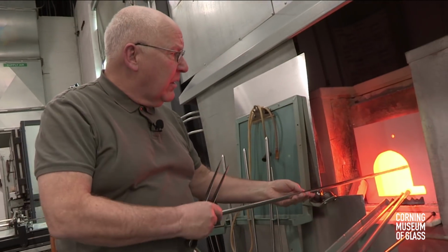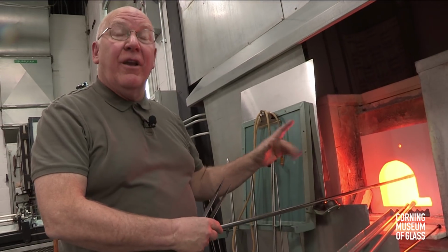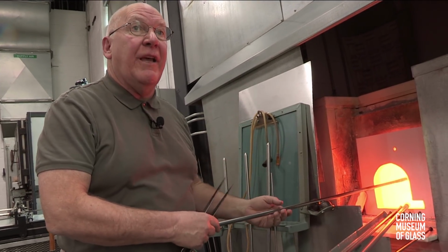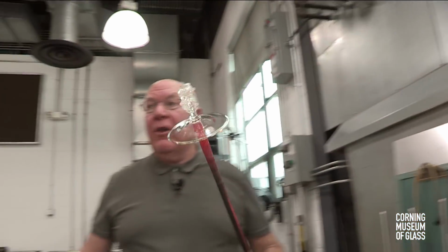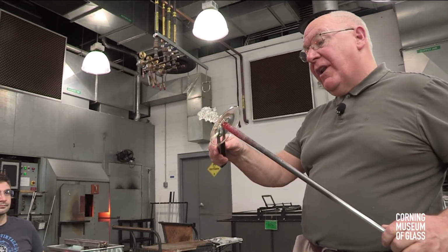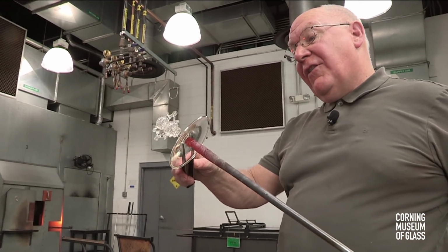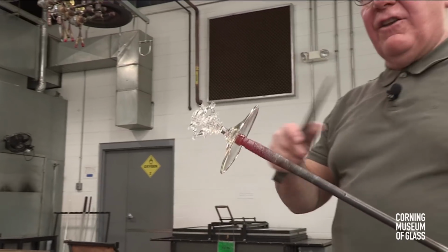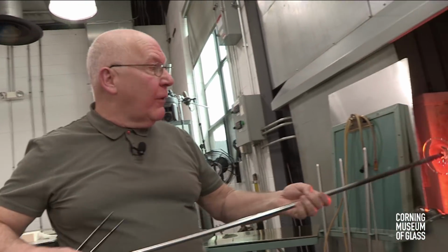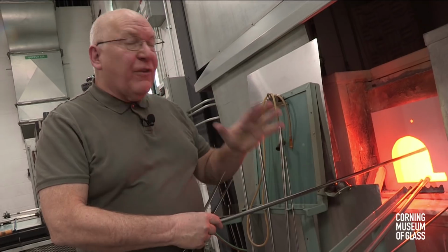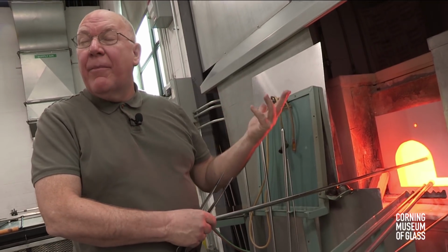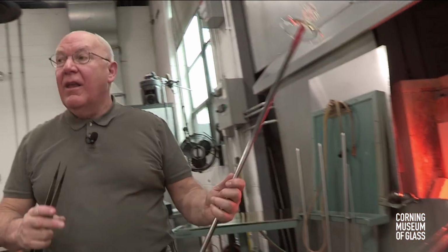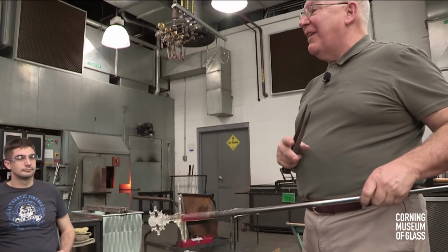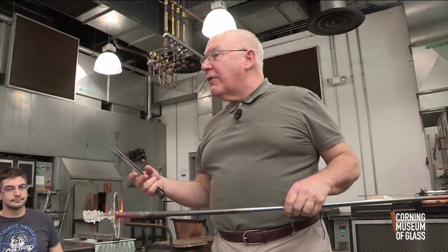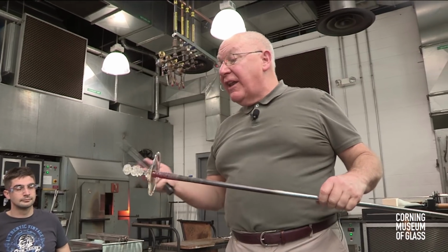But when I reheat the foot, especially because the foot is extremely subject to thermal shock, it won't crack. If I turn that to 945 and do what I just did, the foot would crack. So it's a very specific temperature, and the number is only meaningful in this room for that appliance and for this glass. So you have to test every kiln that you use for a pickup kiln by doing a slump test.